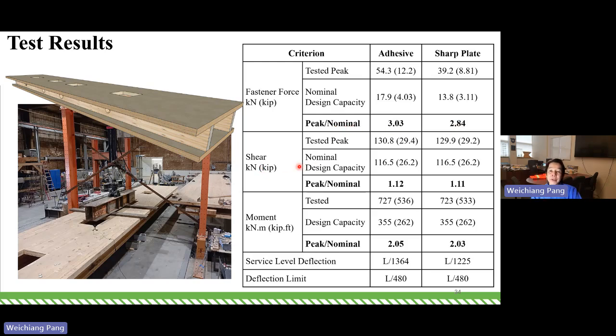For the shear, it's mainly carried by the glulam beam here. And then with the access hole, you actually have reduced shear capacity limited by this hole here. The nominal design value, what we think the design value is, and then the tested shear capacity. The ratio is about 1.1. As you can see for moment, we have way higher moment capacity than the design value.